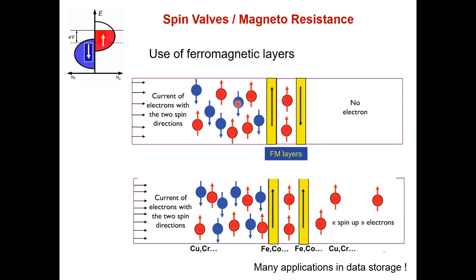And this concept of controlling the current is also connected to the concept of magnetoresistance, because by just changing the magnetization of the second ferromagnet, you can control the current flowing across your device. So it's called a magnetoresistance. And this is actually what we find nowadays in all the data storage applications, like in the magnetic recording, in your hard disk, in your computers. Those are the kind of spin valves that you find in your devices,